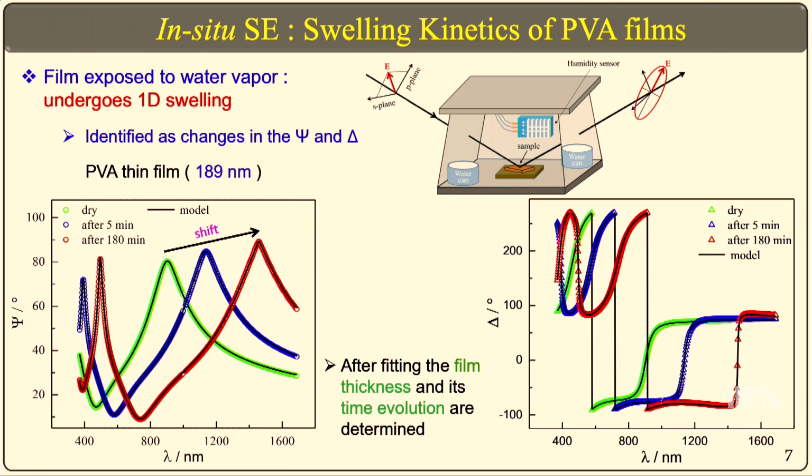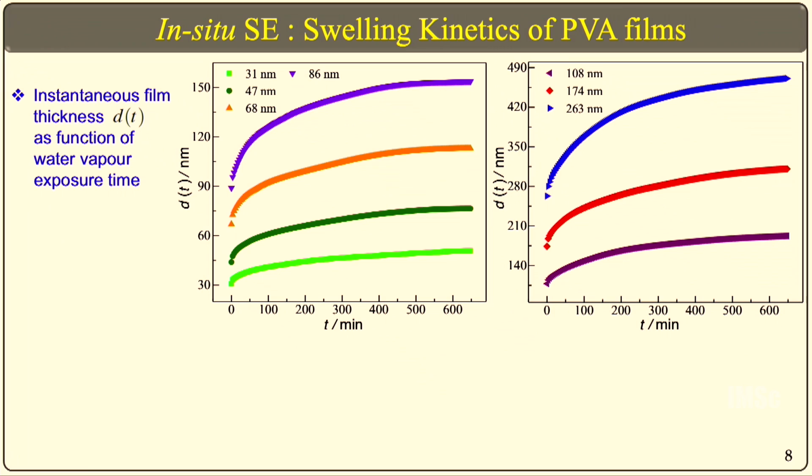No, they are different, sir. Actually, it exponentially decays down. Generally the polymers have a higher refractive index than water. So when swelling starts, the water diffuses in, and the overall sample's refractive index goes down. So we see an exponential fall, because if you look at the swelling also, we have initially a very sharp diffusion, which is generally known as Fickian diffusion. It diffuses very fast because of the concentration gradient, and the later part is basically the polymer relaxation.